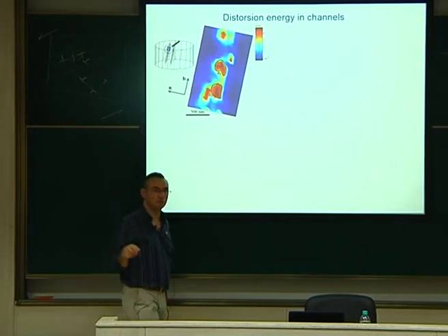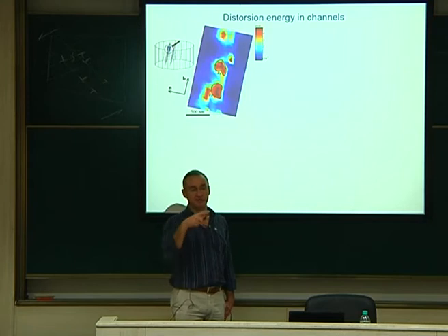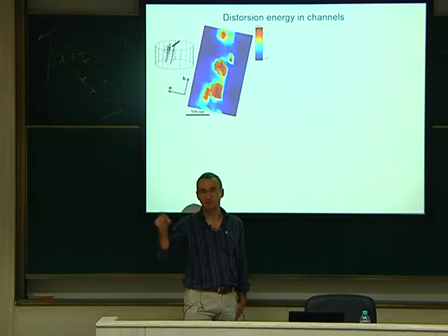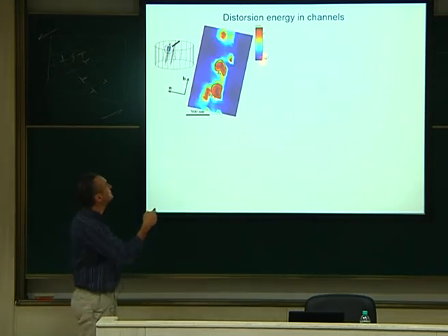You see the double contracted product between sigma and epsilon. So in our case, we have sigma. So we'll take sigma, c minus 1, sigma. We replace epsilon by c minus 1 sigma to have just a function of the stress. The stress, we have it everywhere. So this is the stress tensor to the squared, like this.